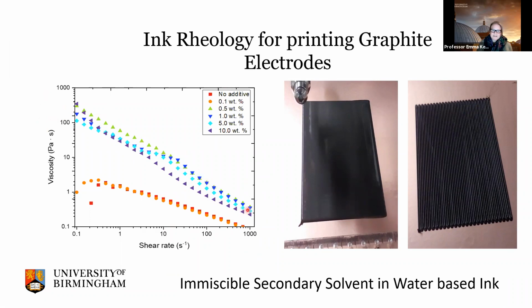This is a very similar technique to what's used for things like face creams. A secondary solvent is added to change the thixotropy and the feel of your cream as you make it. And so we're using a very similar method here to change the rheological properties and the slumping to make sure that we can get defined deposition as we print our electrodes.